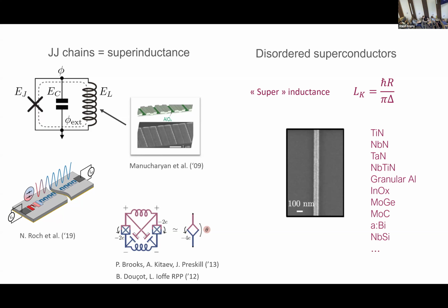The other advantage, in terms of scalability, is that those chains are super long, therefore they have a self-capacitance, which means they can have self-resonances, which can be low in frequency and can mess up your qubit spectrum or interfere, and you don't want that. With a superinductance made of a disordered superconductor, this becomes much more compact, and these self-modes can be pushed to much higher frequency. So these were some of the possible applications.